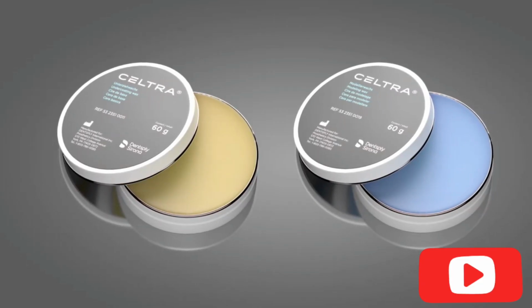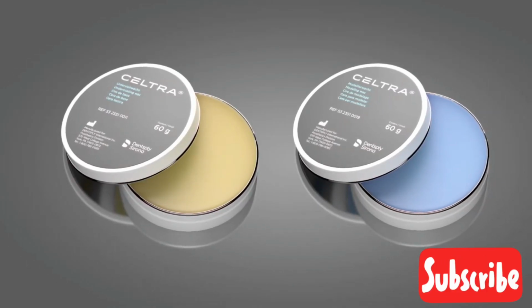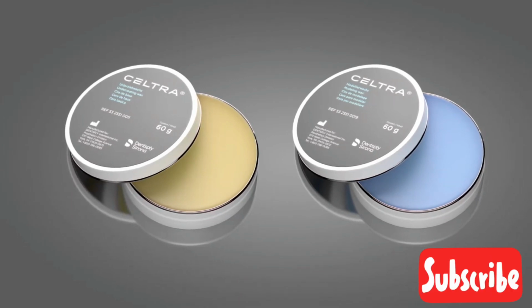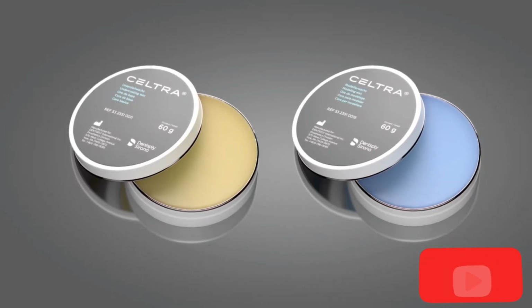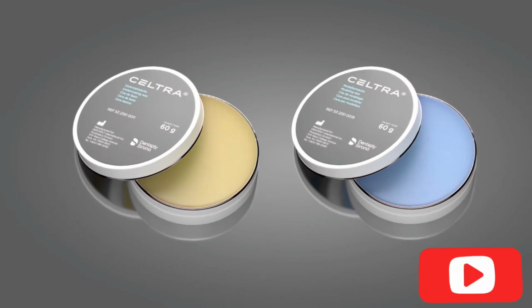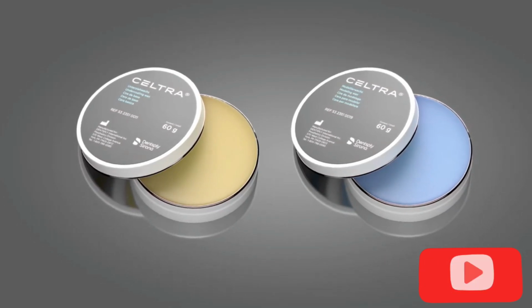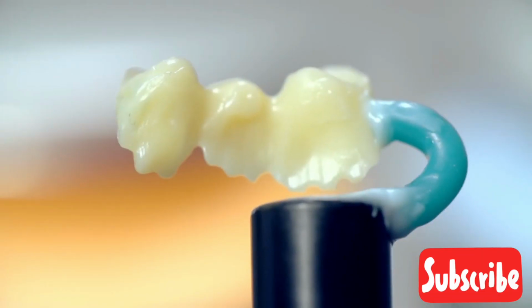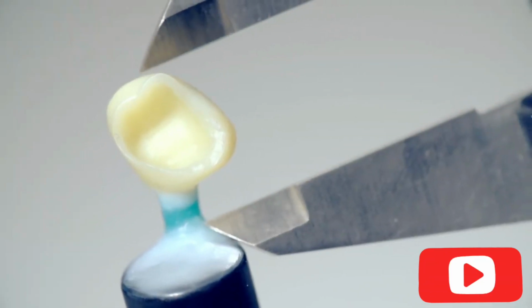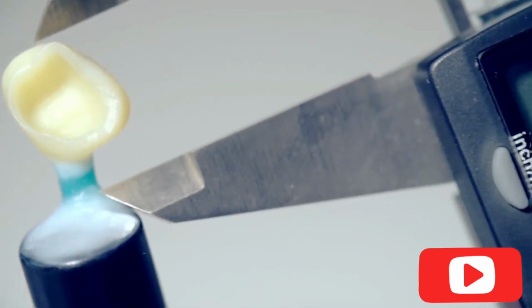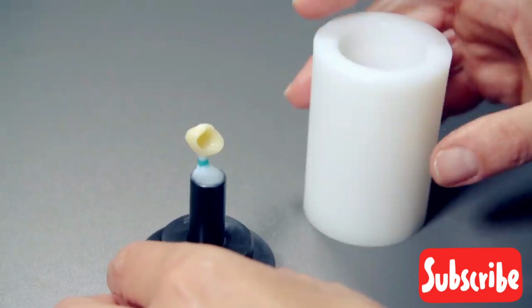We recommend the use of sprueing and modeling waxes developed specifically for pressable ceramics. The sprue for a single crown will have a diameter of 3.5 millimeters. In the case of bridges, we use a piece of pressing wax wire with a diameter of 4 millimeters. The height of the sprue and object combined must not exceed a total of 16 millimeters.